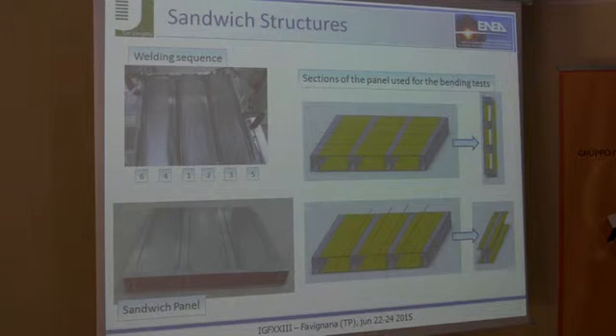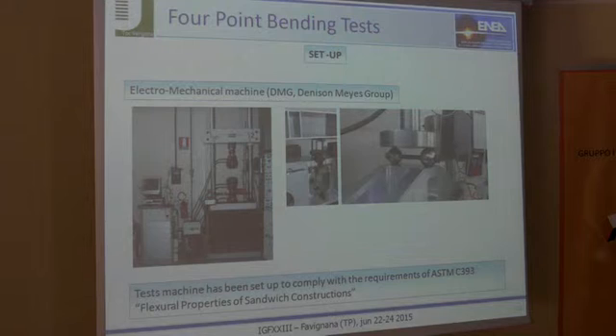Now, the sandwich structures. We realized a sandwich welding together 4 extruded profiles and 6 sheets. And on the right, you can find the section of the panels that we used for the mechanical characterization. The mechanical characterization of the sandwich panel was performed by 4-point bending tests in the two orthogonal directions of load, and we used an electromechanical machine, and to measure the displacement of the sandwich, we used a linear variable displacement transducer.